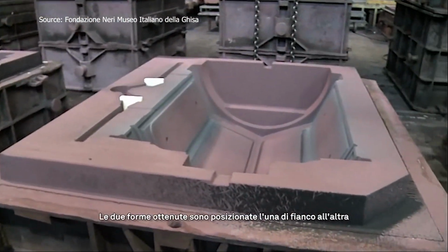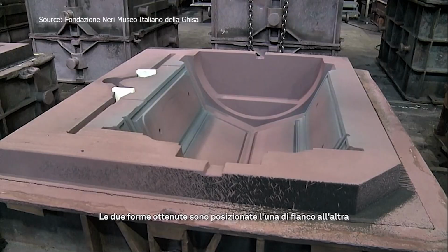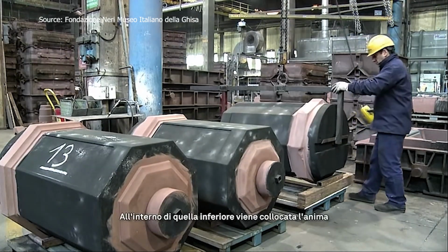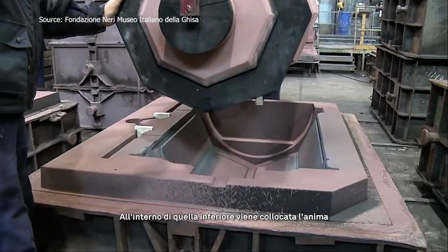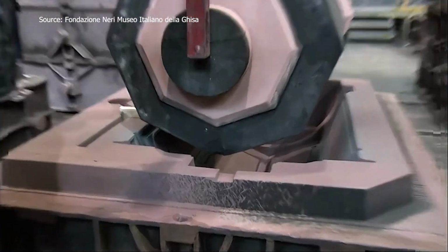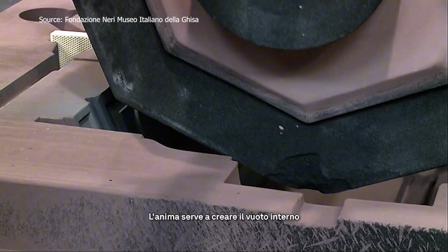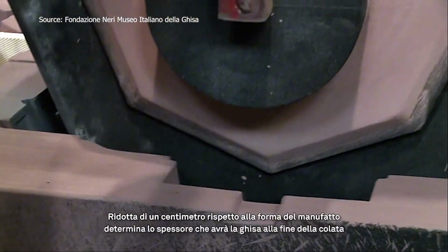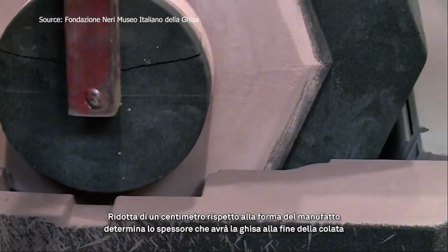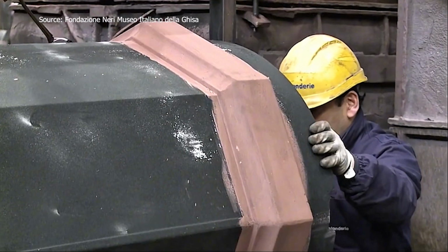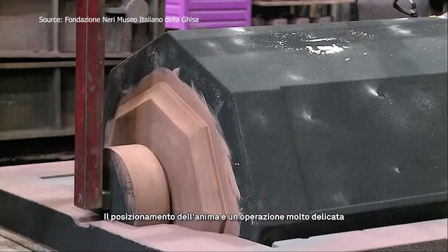The mold surface is then treated with an iron oxide coating, enhancing the quality of the cast iron surface. This coating forms a protective barrier that also improves thermal resistance. The coating is dried in a furnace. The 2 mold halves are positioned side by side, and the core is carefully placed within the lower half. Positioning the core is a delicate step.